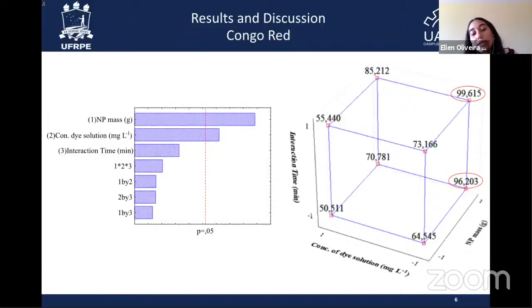It can be observed that the tests that provide the highest percentages of adsorption were test 2, which combines the higher mass, the lower concentration, and the lower time, and test 6, which combines higher mass, lower concentration, and higher time. Both tests showed values greater than 90% of adsorption. As test 2 was performed with less time, it should be chosen since the energy cost will be lower,